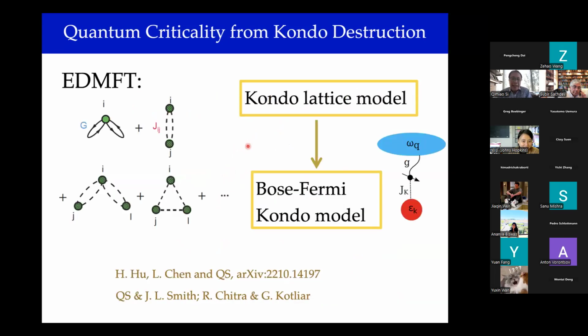And we've been studying this using an approach that incorporates the dynamical interplay between the RKKY interactions among the spins and the Kondo effect, with a scheme that is inspired by the dynamical mean field theory, but incorporates this dynamical interplay, and it is systematic, etc. And so this approach allows us to study the fate of the Kondo effect of the local moment coupled to both the fermion bath and being in the environment of the fluctuations induced by the RKKY interactions.